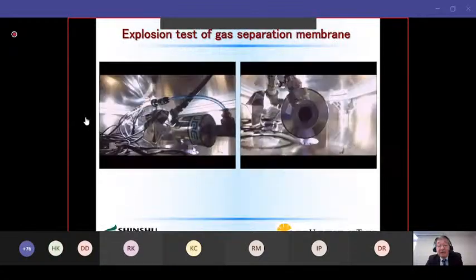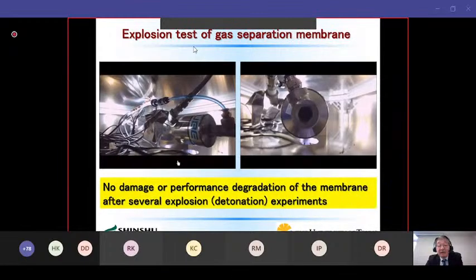And maybe some of you are afraid that the gas separation membrane might be destroyed by this kind of explosion. Actually, in this case, this membrane is working, and we cause an explosion intentionally through this line, like this. Okay, and we have made a window to see the inside of this gas separation membrane, and now you can see the inside. But as you see here, there seems to be no damage, and actually we observed no damage or performance degradation of the membrane after several explosion or detonation experiments. That means that if we design suitably, we can avoid any damage from an explosion if it takes place.